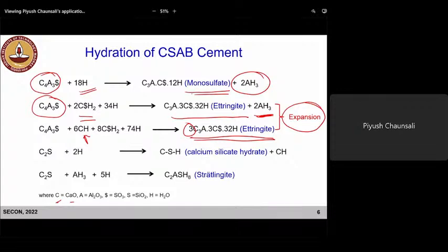Since I mentioned that CSAB cement may also contain belite, C2S hydration will lead to formation of CSH and calcium hydroxide, as we know. In this case, since AH3 is formed, C2S can also react with AH3, aluminum hydroxide, and form another phase, C2ASH8, stratlingite. So you can see the hydrated phase composition of CSAB cement is different than Portland cement.